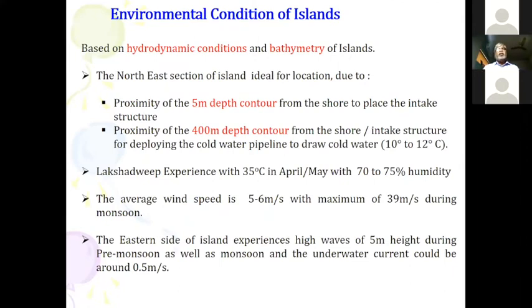The environmental conditions have been studied. A proximity of 5-meter depth contour was there on the shore for the intake structure, and a 400-meter deep contour from the shore to take in the water, where you get a temperature of about 10 to 12 degrees. It was done during April, May.